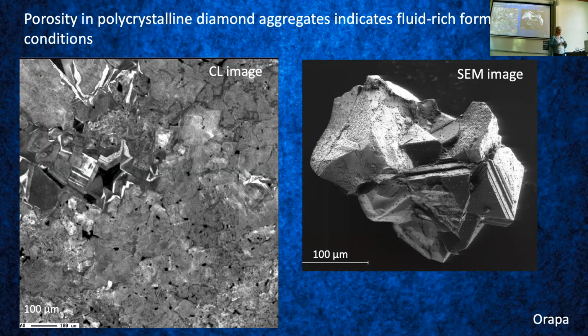It's also hard to look at these inclusions because they're mostly black, as you saw. You can't see through, so you basically have to cut. You have to either laser cut or do something else. We chose to do focused ion beam cutting, and cutting a focused ion beam foil from a diamond takes about 10 hours, and you pay by the hour, so you're a bit limited by the budget. What they also have, and that's just another SEM image here, is that they're very porous. They have up to 30% porosity, and they're formed in the upper mantle.